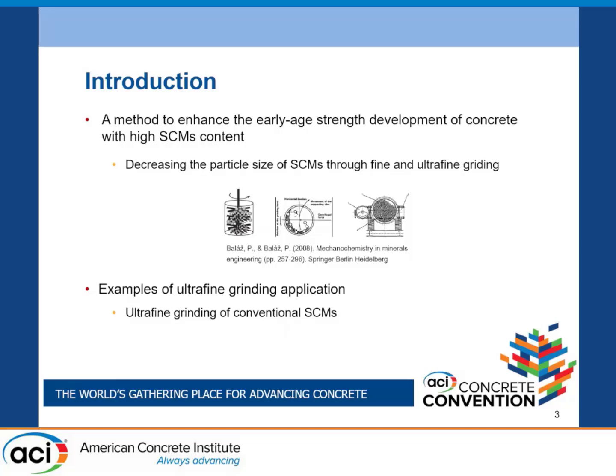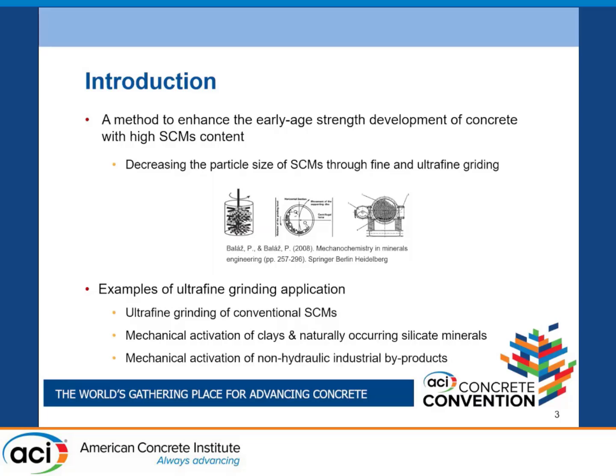of the mixtures. It is also extended to mechanical activation of clays or naturally occurring silicate minerals, making them reactive so they can be used as a new source of SCMs. And some non-hydraulic industrial byproducts, for example steel slag, if we do grinding and mechanical activation, become reactive and can be used as SCMs.